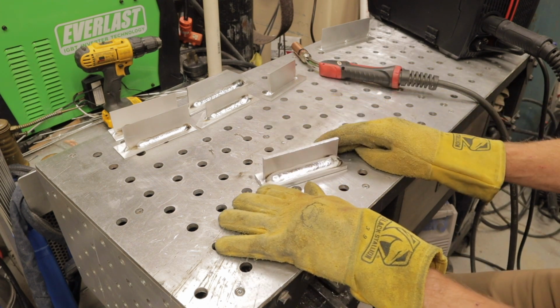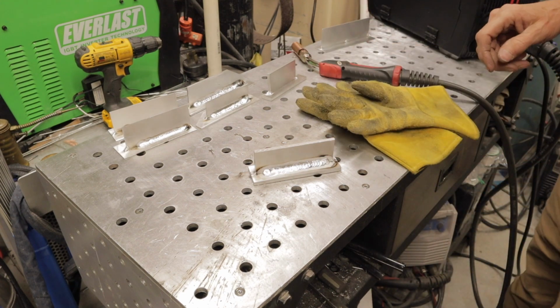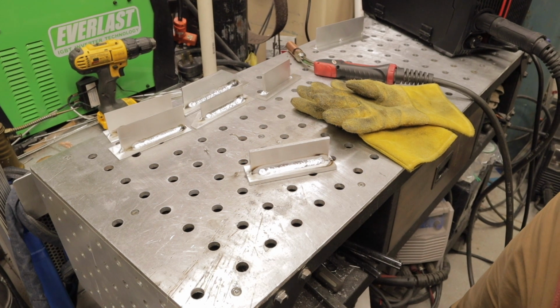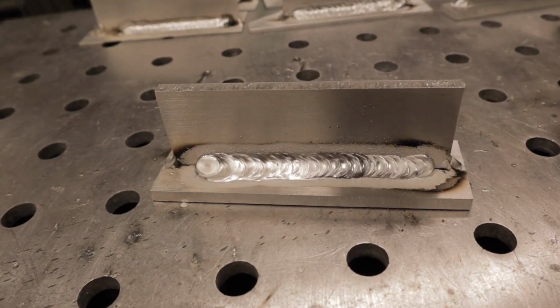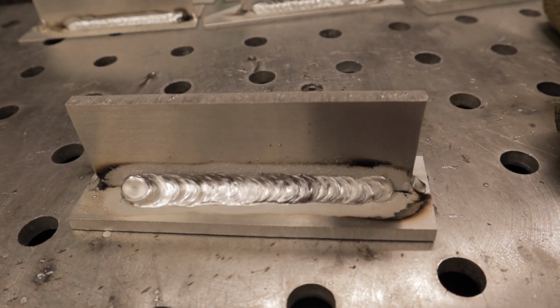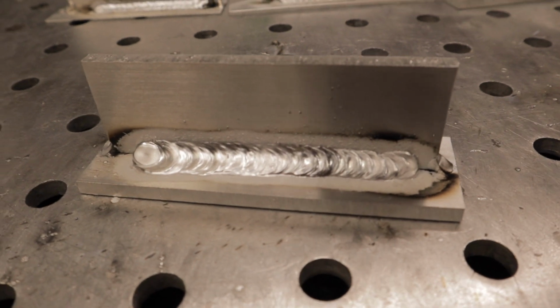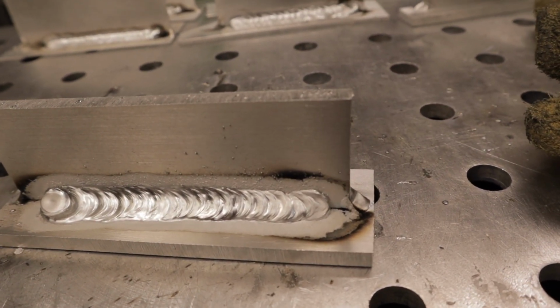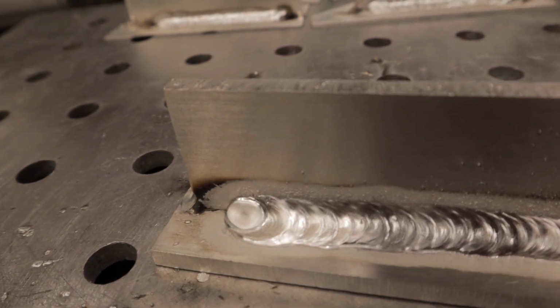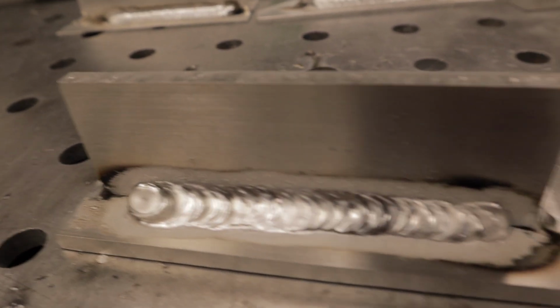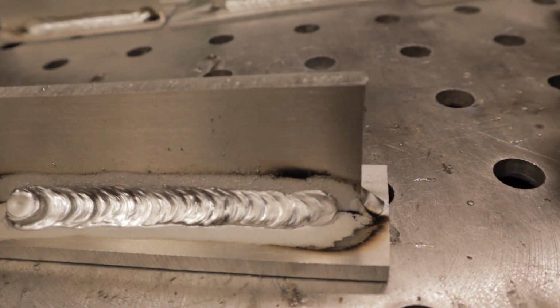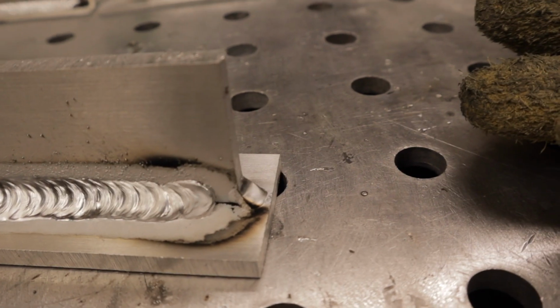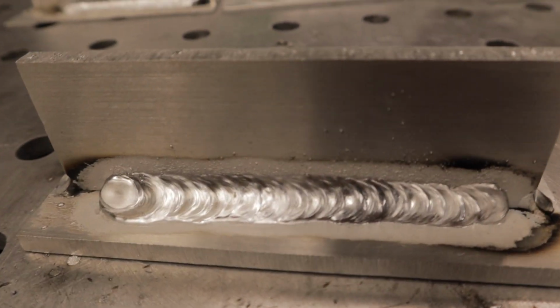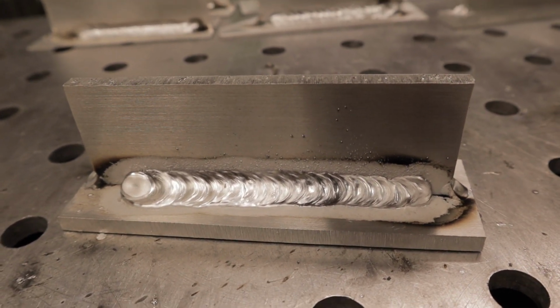All right. Yeah, and take a close look at this. So, this one I've got programmed pretty darn close. You can see that with the higher flow of argon, you're getting a lot more cleaning. That is one of the benefits of that higher argon flow. You can see that I've got a crater fill at the end. That's the beauty of the 4TL. And that's a nice looking MIG weld. Not a bunch of splatter all over, not a bunch of soot. This thing welds very clean. I'm very impressed. Alright, let's run another one so you can see more of the 1/4 inch.